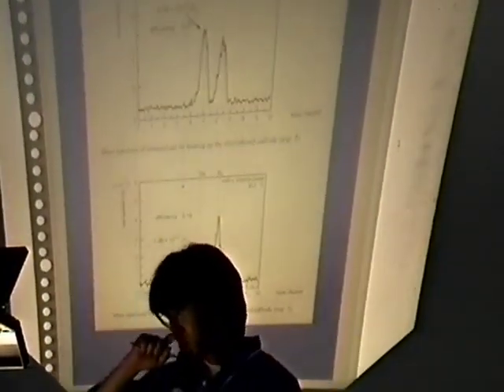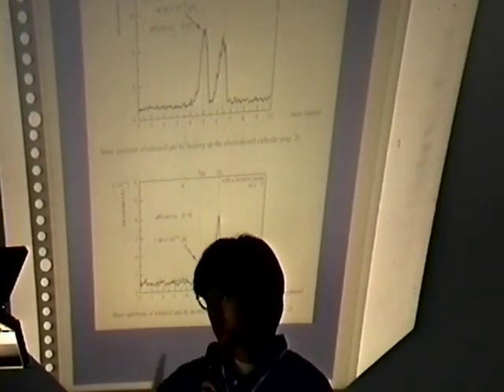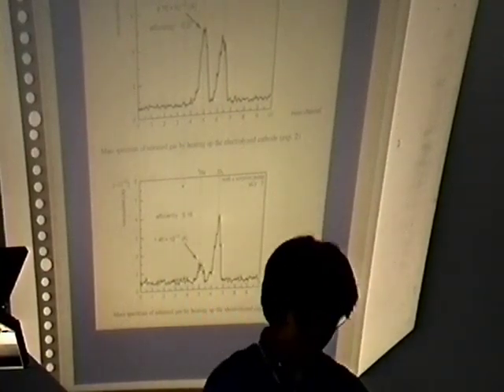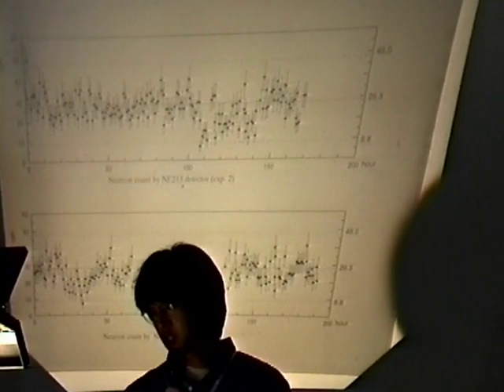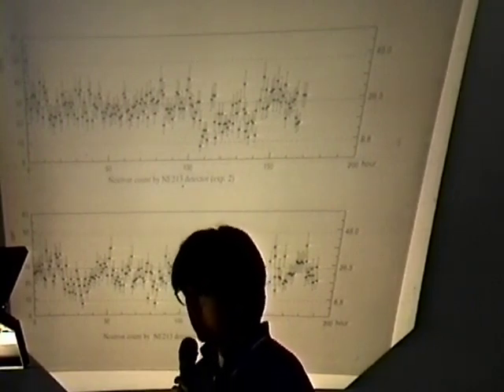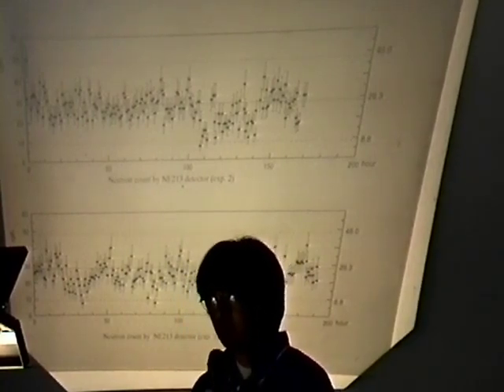And we also detected helium-4 in EXP2 and EXP3. I show the results. These are mass spectra of EXP2 and EXP3. This is the helium-4 peak. And next I show the results of the neutron detection in EXP2 and EXP3. We can detect a meaningful increase of the neutron counts in this experiment. So therefore, we can detect the correlation between helium-4 generation and neutron emission in this experiment.